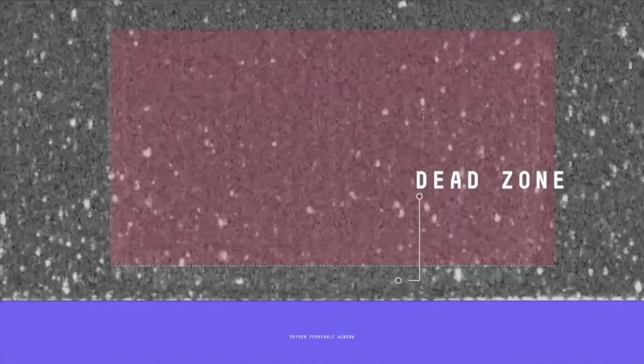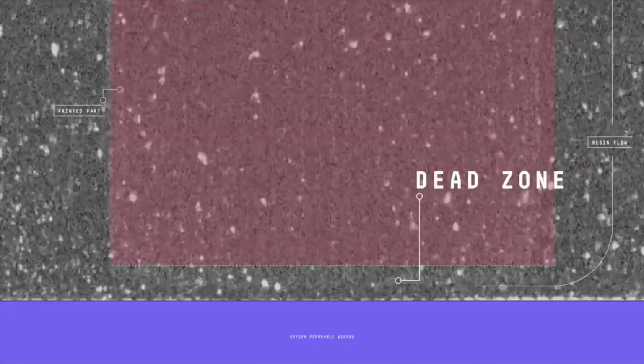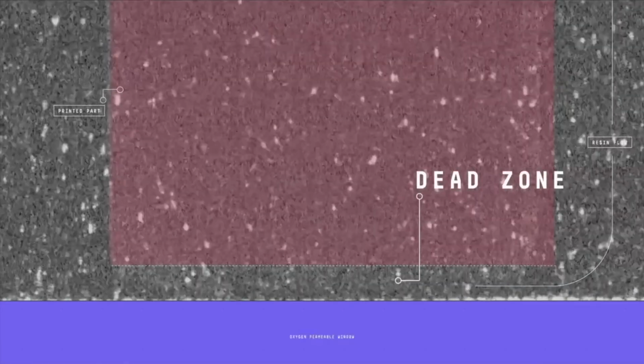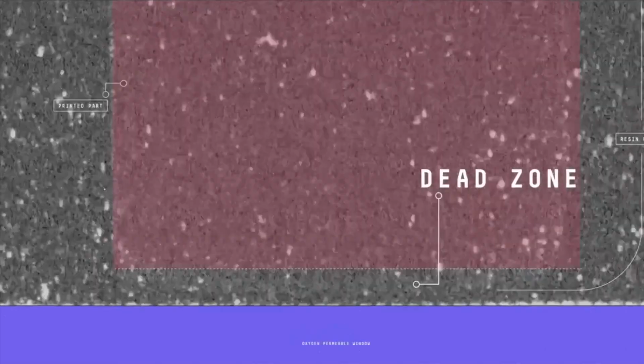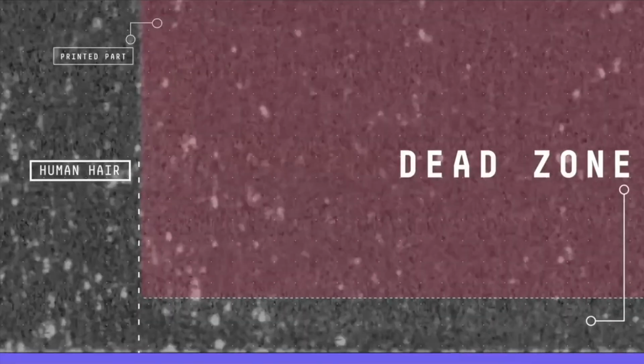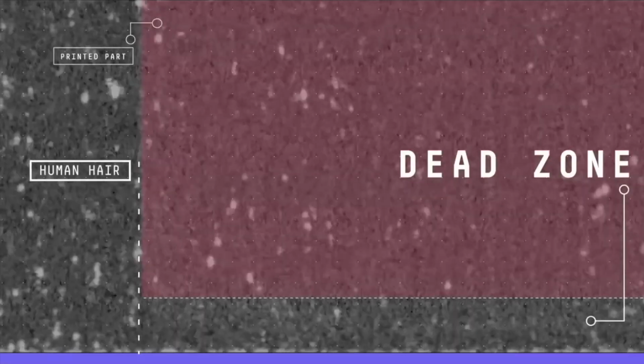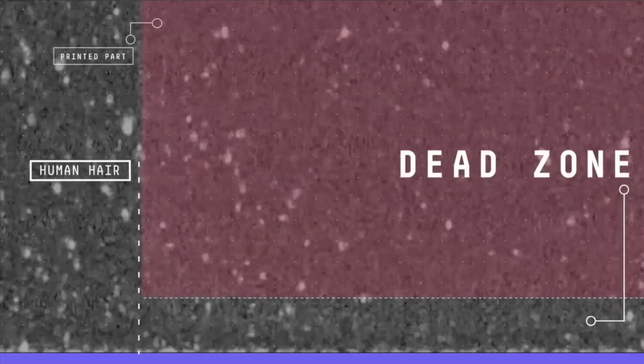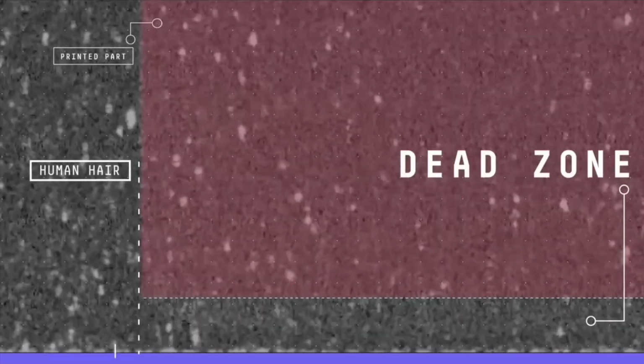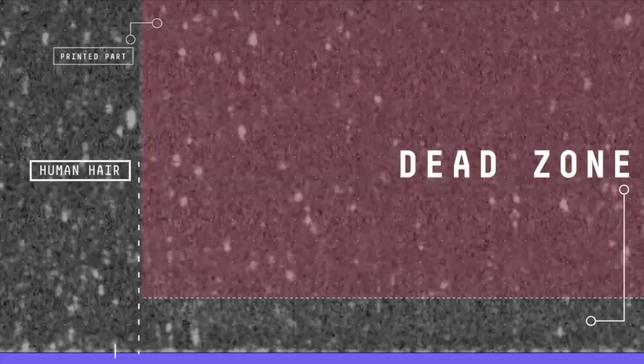And here's an actual image. This is optical coherence tomography. And we put a contrast agent in the resin so you can see the flow of liquid that's forming. And you see there's a negative pressure in the middle of that part as it's drawing resin into the gap. That gap is about 20 to 50 microns, depending on how we run the printer. And it allows resin renewal automatically. And this allows a printer to go substantially faster. Okay?